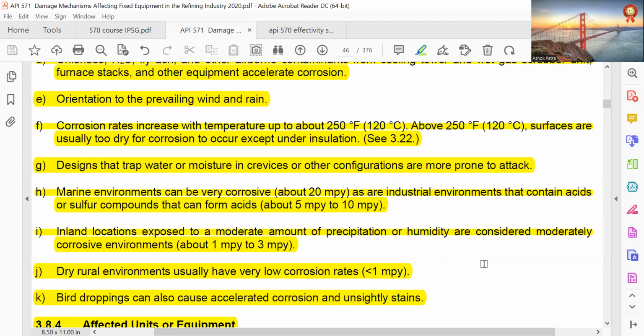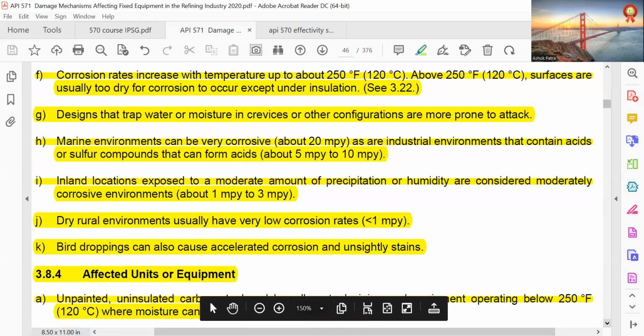Marine environments can be very corrosive, about 20 mpy, as are industrial environments that contain acids or sulfur compounds that can form acids, about 5 mpy or 10 mpy. Inland locations exposed to a moderate amount of precipitation or humidity are considered moderately corrosive environments, about 1 mpy to 3 mpy. Dry rural environments usually have very low corrosion rates, less than 1 mpy. Bird droppings can also cause accelerated corrosion and unsightly stains.